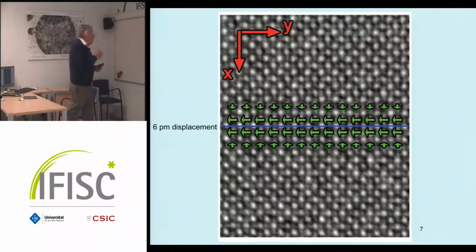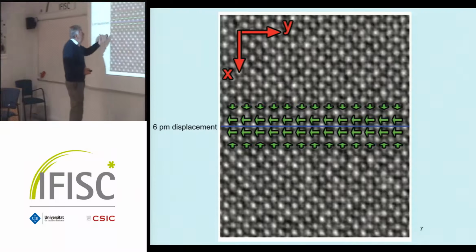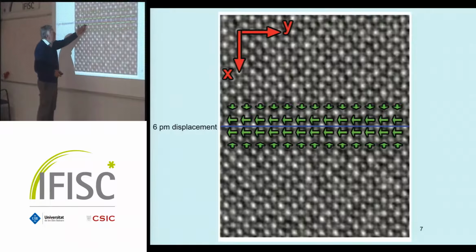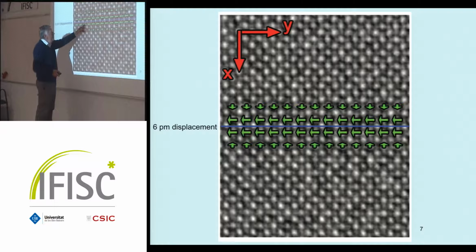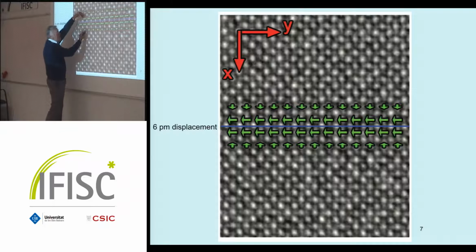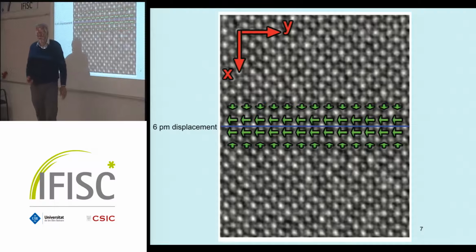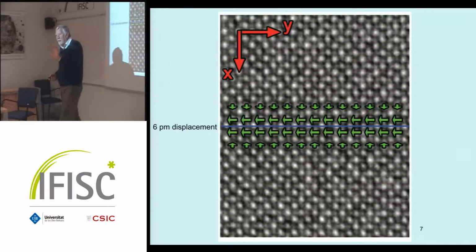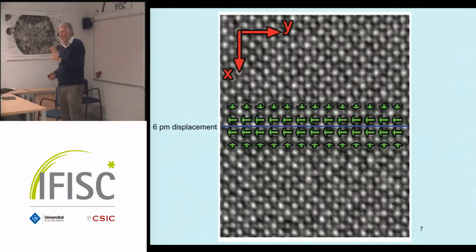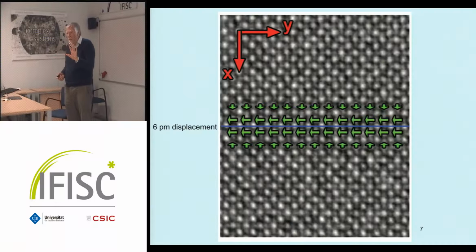So here, that's now a slightly higher resolution, and the white spots are indeed the titanium, and you can see that's the pattern. So all the pattern, all the titanium go in that direction. There's a relaxation going in that direction, and so forth. How the exact pattern is not important for you, because we have several materials now which can do that. But the importance is there is a dipole.